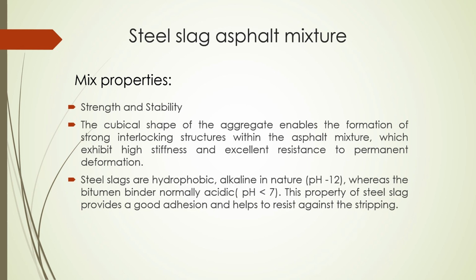Steel slag is hydrophobic and alkaline in nature, meaning its pH is approximately 12, whereas bitumen binders are normally acidic, with pH less than 7. This property of steel slag provides good adhesion and helps to resist stripping.